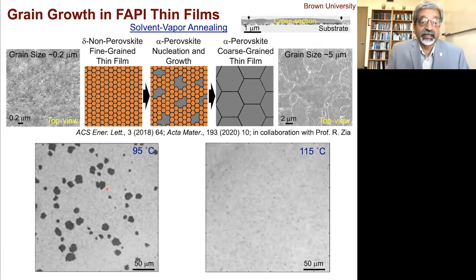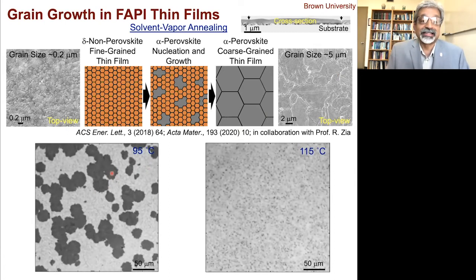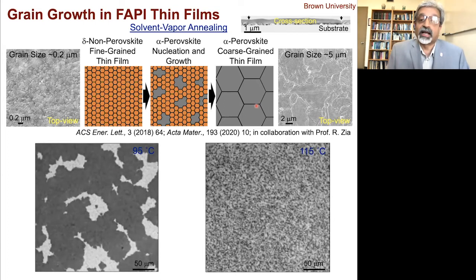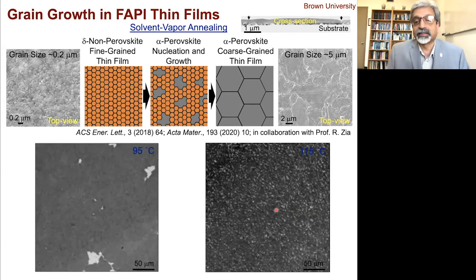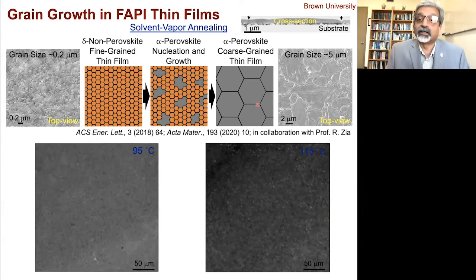And here are some videos that basically show what happens when you change the temperature for the nucleation. So this is what we need, where you need a low nucleation density, because when they meet, they'll form large grains. If you have high nucleation density, then when they meet, they will give you fine grains. So this is what Srinivas used to get something like this, right?